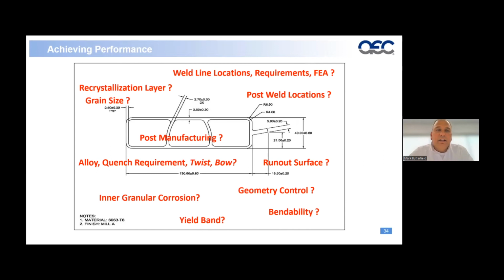So when I see a print like that, there are a lot of questions I have. We talked about grain structure earlier. What is the grain size? Is there a requirement or a specification relative to the recrystallized layer? For example, is it fully fibrous with a 20% layer? Weld line locations. Is there an understanding of the weld lines, the seam welds that are in the extrusion die itself? And is there an impact to that relative to the secondary processes? For example, for your post-weld locations, what we don't want to do is start a post-weld on or end on a seam weld within the extrusion. So understanding that up front is just an additional benefit. Seam welds can typically be moved around within an extrusion profile, but it needs to be understood up front.